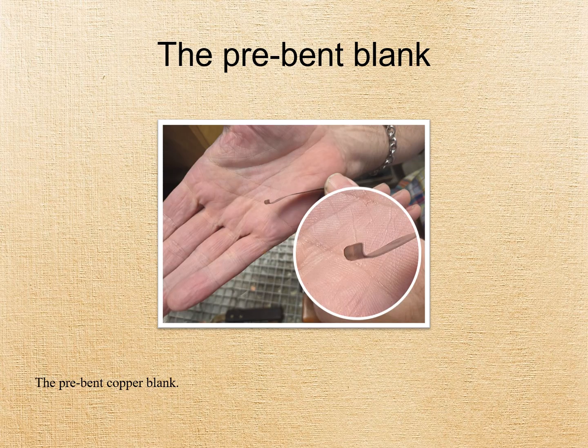Here you can see the pre-bent copper blank. You can see that it is quite open. I had to bend this over a little bit more with a burnisher to get the smaller curve. I will be grinding a bit of metal off the end of the anvil so I can get a sharper initial bend with just the anvil.